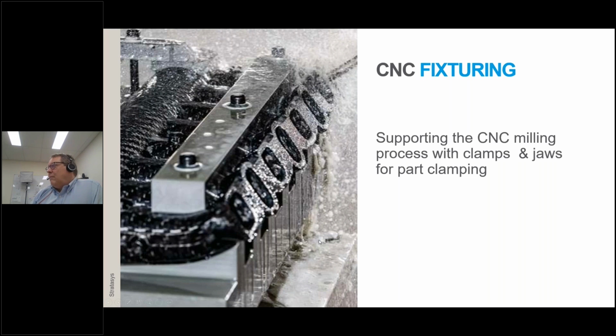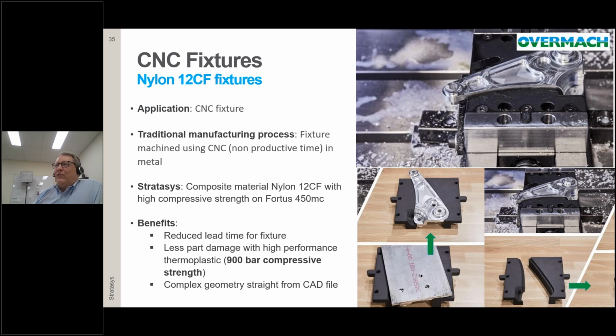CNC fixtures, again, one of these applications which is really a burden, and whoever actually tried to clamp a 3D shaped component onto a milling machine and into a vise knows what I'm talking about. We have today great applications from different customers printing 3D shaped components in order to replace the standard jaws with 3D printed jaws. The nylon carbon fiber can withstand huge hydraulic vise clamping forces. So you can really clamp and secure the part on your milling machine, also for heavy milling application. And a very important message, you print the jig away from your expensive CNC milling machine. I think this is one of the most important assets.